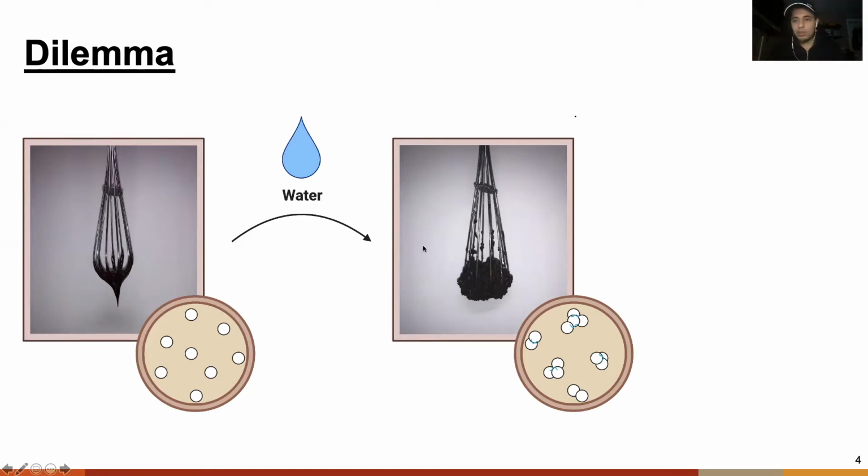Now, when you add water to the system, what essentially occurs is that the sugar really loves the water. And so the water binds to the sugar and starts to solubilize it and create a sticky coating on its surface. What this sticky coating does is attract other sugar particles and cause them to aggregate together. This aggregation process creates particle aggregates, which behave much larger than they really are, and they increase the internal friction of the system itself. As a result, everything has a much harder time flowing past one another, and so overall, the chocolate will be much more viscous.